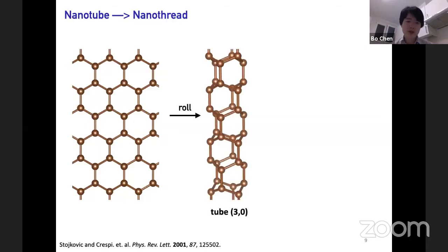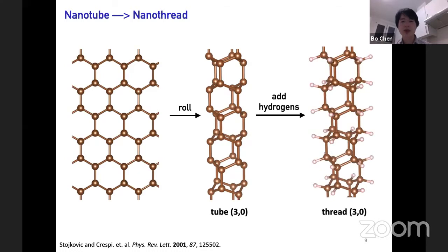And you can see from this picture that because the tube is so thin and the curvature on the surface is so large, the sp2 carbon, the planar tricoordination, is so distorted. It looks like these carbons are already in sp3 state. It looks as if there's a dangling bond here and a dangling bond there. So they thought, why don't we just cap those dangling bonds with hydrogen atoms to stabilize the structure? And after doing that, this is what they get. It's a very beautiful structure, the (3,0) nanothread.